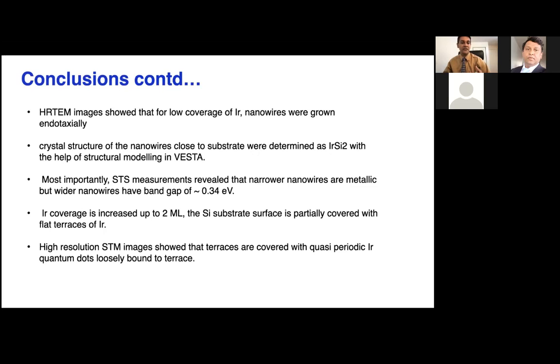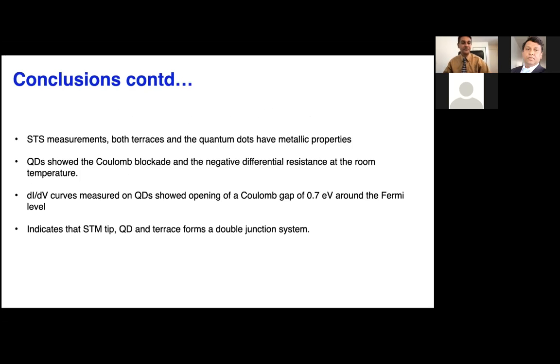And if we increase the coverage up to 2 monolayers, we found quantum dots on the surface, quasi-periodic quantum dots. STS measurements on both the terrace and the quantum dots indicated that the quantum dots show metallic properties, with a Coulomb gap for the quantum dots of around 0.7 electron volts.